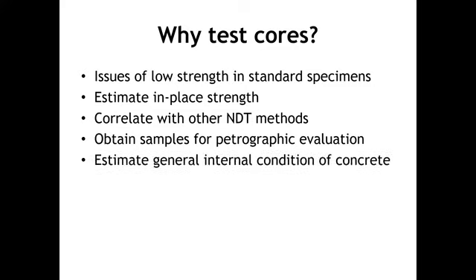Only that level of concrete needs to be removed. Otherwise, let's take a condition: the chloride ions have penetrated up to 25 millimeter. I draw a sample up to 40 millimeter, and this 25 millimeter sample and 40 millimeter sample got mixed together. When I do the test at the lab, I will not be able to get exactly what is the concentration of chloride ions in that. So it is always better to go for different depths and to write your specification up to what depth you need to remove the concrete cover thickness, because chloride induced corrosion is more dangerous. It was very well explained by the Professor.